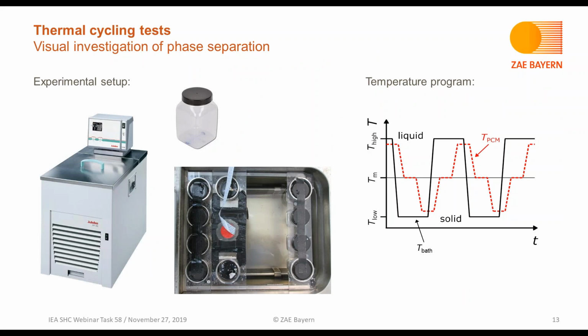The next step is to perform thermal cycling tests. The idea of thermal cycling tests is to validate that the PCM can be used over many heating, cooling, melting, and crystallization cycles, and thereby take into account the requirements or the conditions of the applications. What we are doing in thermal cycling is shown on the right, the temperature program. That means we have the PCM, and this is subjected to repeated heating and cooling.